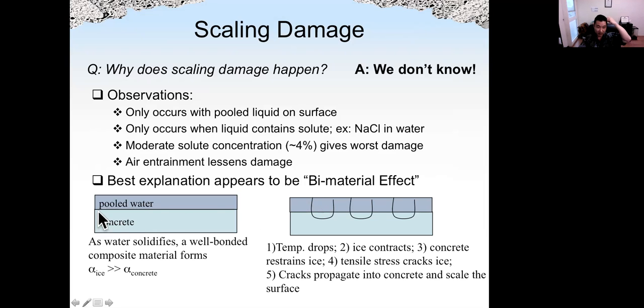So let's say here we have a pooled water. Inside that pooled water, we have salt. And we have concrete layers beneath that pooled water layer. When the temperature drops below freezing, the water becomes ice, and that will form a well-bonded composite material. So we have an ice layer on top of the concrete layers. Here this is alpha ice, the coefficient of thermal expansion of ice, which is much larger than the coefficient of thermal expansion of concrete.